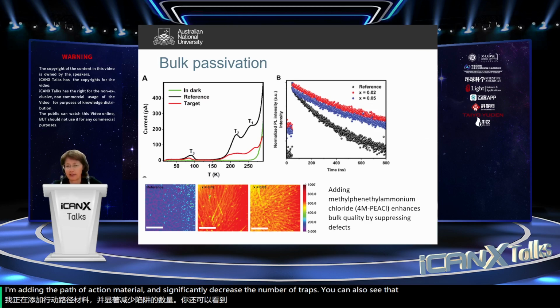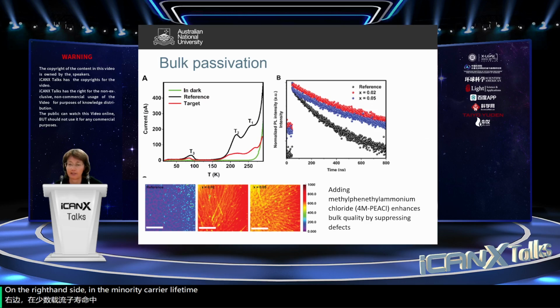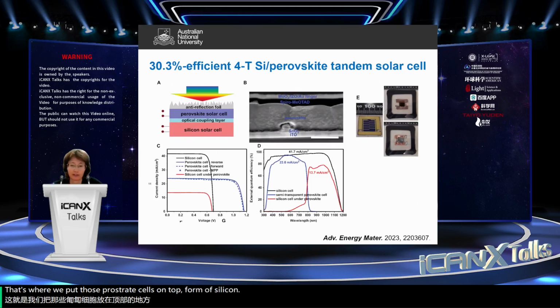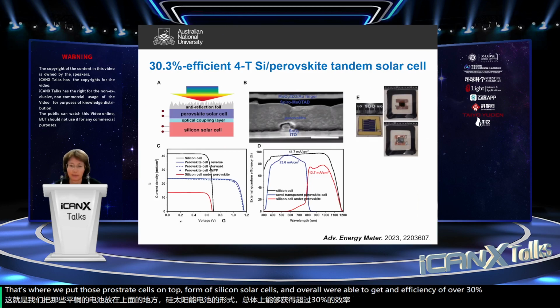You can also see that on the right-hand side in the minority carrier lifetimes, the photoluminescence decay. So the photoluminescence decay happens much more slowly for the target device, indicating better electronic quality. And finally, in the bottom images, you can see the photoluminescence steady state intensity, and you can see a much higher photoluminescence intensity, again indicating better bulk quality. So we put those perovskite cells on top of silicon solar cells, and overall we were able to get an efficiency of over 30% by having the perovskite solar cell with improved bulk quality on top of a high efficiency silicon solar cell.